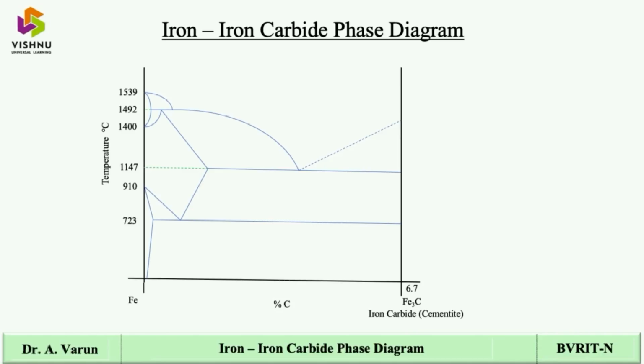Now like I said, above 1539 degrees centigrade we have liquid, which is this line, our liquidus line, above which everything will be in the liquid state. Then below 1539 degrees centigrade at this location, you'll get delta iron. Like we have already discussed, from 1539 to 1400 degrees centigrade, we have delta iron. Below delta, we have gamma from 1400 down to 910, which in this case is austenite. We'll come back to that. Then below 910, we have alpha iron, which is ferrite. We'll discuss that ferrite shortly.